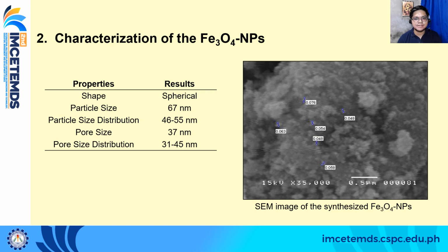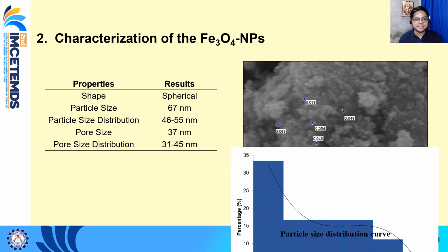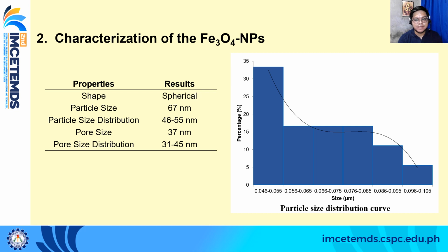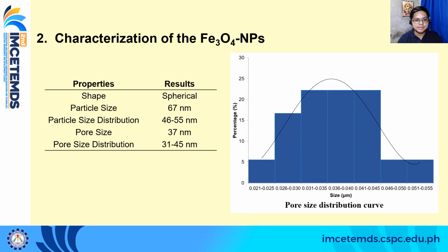Now, this section provides the results on the characterization of the synthesized iron oxide nanoparticles. Using a SEM, or scanning electron microscope, showing on your screen is an image of the iron oxide nanoparticles produced. The shape is spherical, which conforms to the related literatures of this study. As for the particle size, it's at 67 nanometers with particle size distribution at 46 to 55 nanometers. And for the pore size, it's 37 nanometers, and for the pore size distribution, it's at 31 to 45 nanometers. These all conform to the related literatures and prove that our formed iron oxide nanoparticles can be an effective adsorbent for the removal of methylene blue dye.